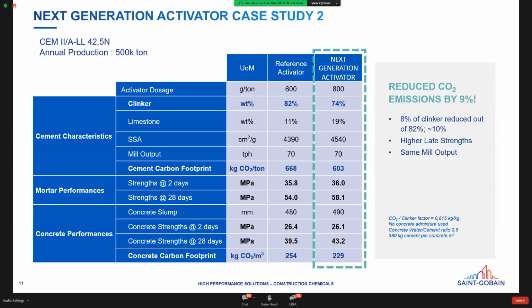The second case study concerns the production of limestone cements. In this example, the next generation activator was used at 800 ppm. It has allowed to reduce the clinker factor of a cement by 8% compared to the cement produced with a reference additive. The strengths measured on the mortar are similar at 2 days, but the 28-day strength was significantly enhanced with the next generation activator despite the significant clinker reduction factor.